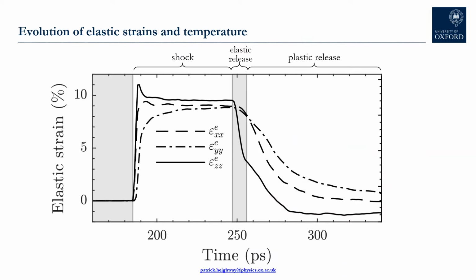In this graph, I'm showing the elastic strain state of the element as a function of time, which I think illustrates quite nicely the whole shock release cycle. So we see that the shock wave strikes the element at about 185 picoseconds, which raises the strains along the 3 coordinate axes to about 9%. The element stays compressed for about 60 picoseconds, during which time the shock wave traverses the remaining 200 nanometers of the crystal, breaks out from the rear surface, and then launches a release wave back into the crystal that first encounters the element at about 247 picoseconds.